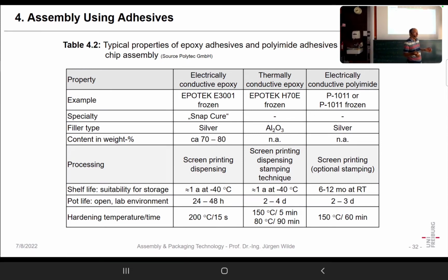I mentioned when you do your household gluing with epoxy, you mix it. That you will not do with industrial epoxy. Industrial epoxy is pre-mixed. And in order to prevent it from hardening from that second on when you have mixed it, you must do something. And the trick is temperature.